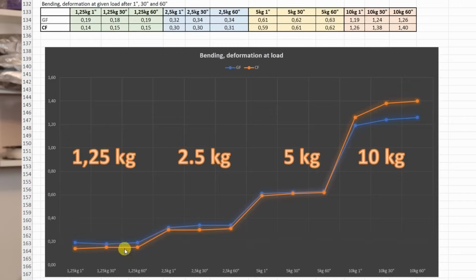It was interesting to see that two fiber reinforced materials act differently. The best example here is that bending test. On smaller loads, the carbon fiber version was better because here the base material takes over the load. And when the deformation became bigger, then partly the fibers take over that load, and here the glass fiber version was better. I believe that partly this is because of different material types, of course, but also I noticed under the microscope that the glass fibers are a little bit bigger in diameter compared to the carbon fiber version.